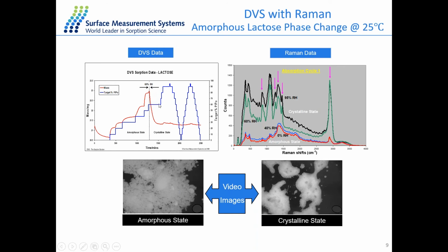And at a specific step here, which is 60% RH, the red line drops a lot, which is due to the amorphous to crystalline phase change. And this phase change didn't show in the second cycle, so it's an irreversible phase change. That's information we can get from the DVS data here.